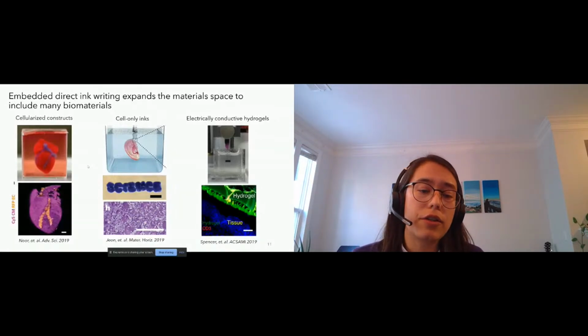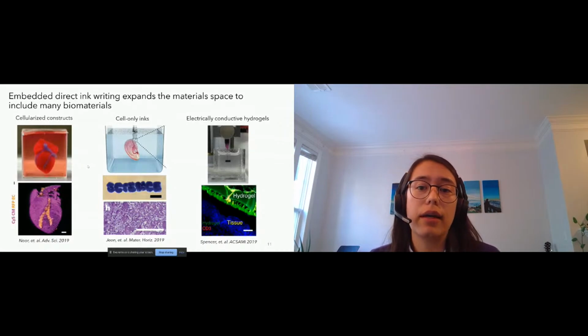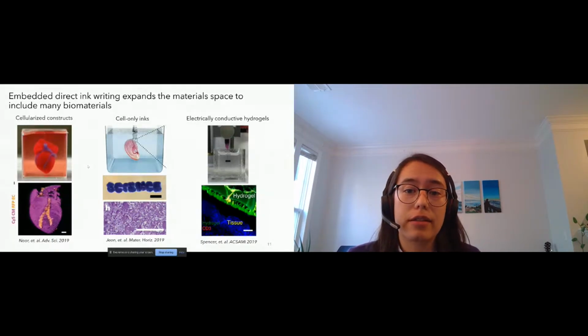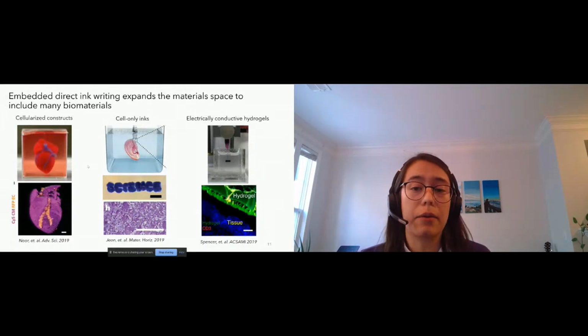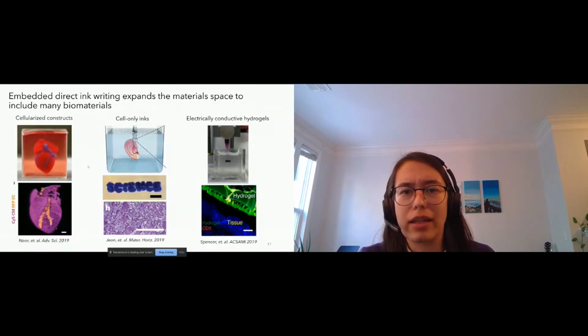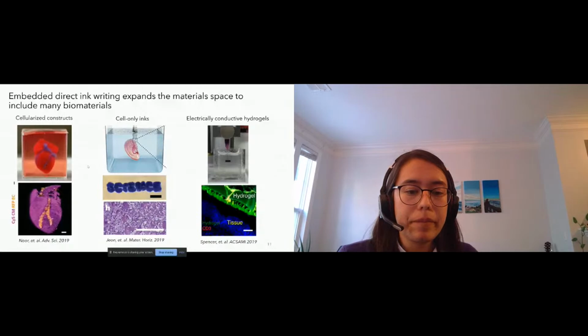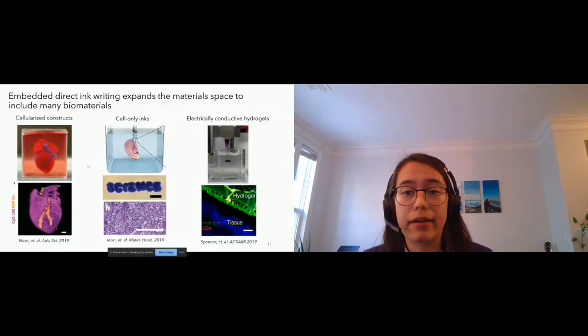And then you can also print functional materials, things like electrically conductive hydrogels, things that are at a low viscosity, where you've already tailored your ink to a certain functional property like electrical conductivity. You can still print that ink by using a support bath, because that support bath takes care of the rheology aspect.